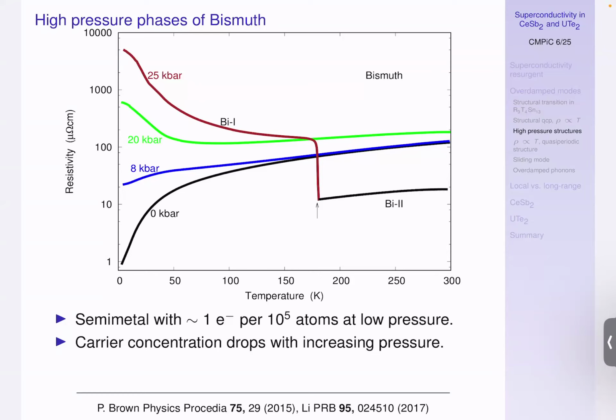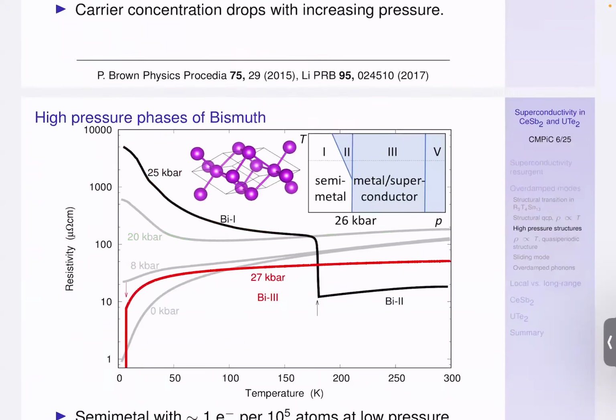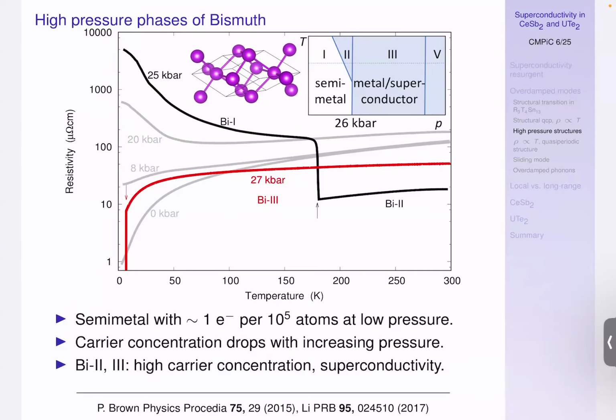Namely, at high pressure, the material undergoes a structural transition into a new phase, the Bismuth-II phase, and then a second structural transition into the Bismuth-III phase, which is the red line, resistivity versus temperature of Bismuth-III. So you go from, as a function of pressure and temperature, one semi-metal phase, which has been mostly studied. There's a slim sliver in the phase diagram of this Bismuth-II phase, and then a wide range of Bismuth-III.